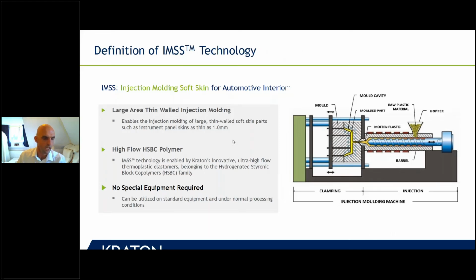As you can imagine, having an instrument panel, and you know dashboards in cars, they're big. You need to have your polymer match those dimensions, and you need to make sure that there's enough flow, so you're reaching also the interestingly shaped corners of this instrument panel. And we put the requirement that there's no special injection molding machine needed, because we didn't see tier 1s invest millions and millions into a new injection molding machine. As a matter of fact, just the mold is already around $1 million investment. So that's already significant enough. So we had to develop high flow HSBC polymers, and that's what we did.